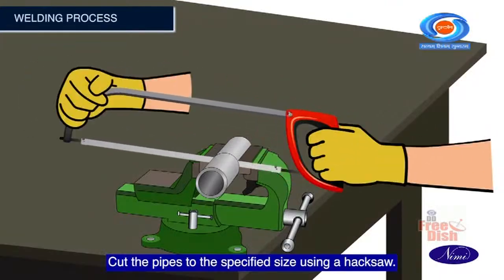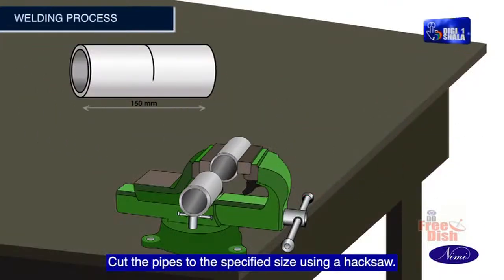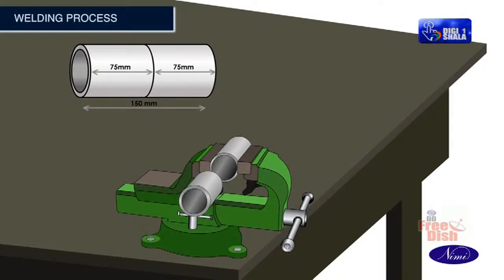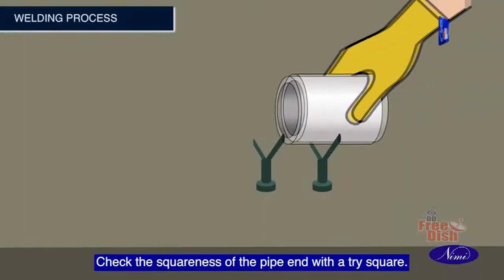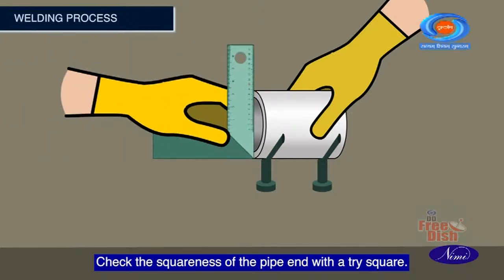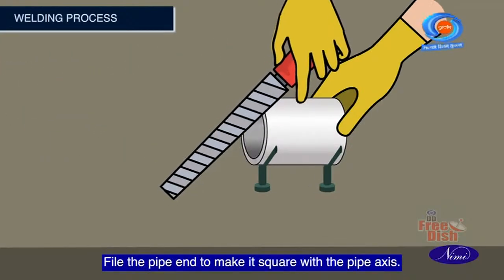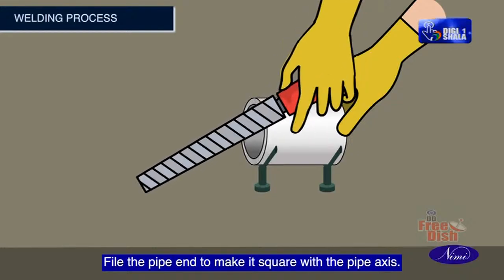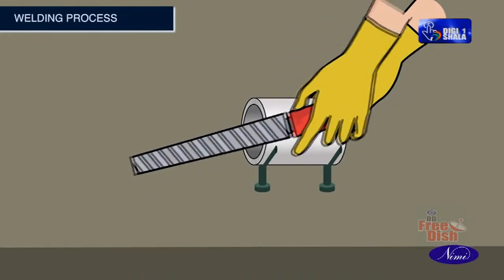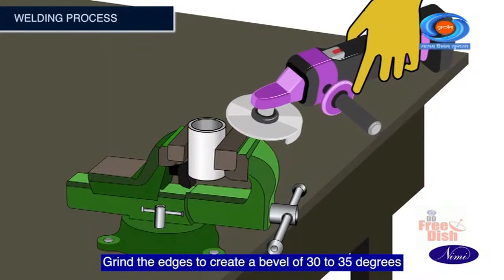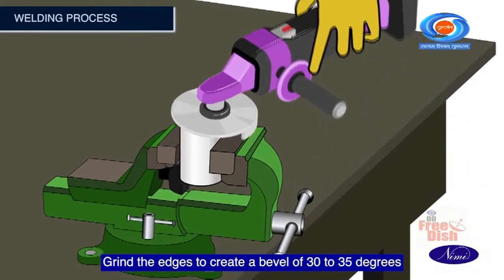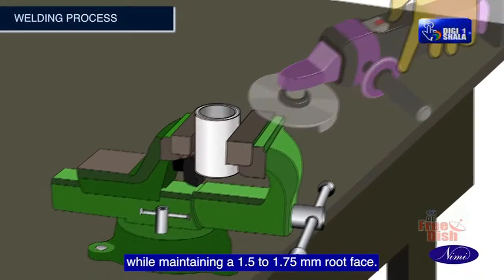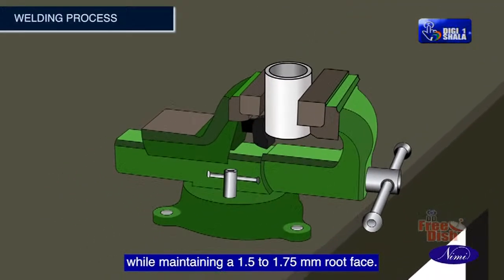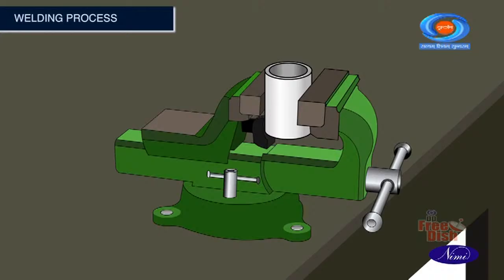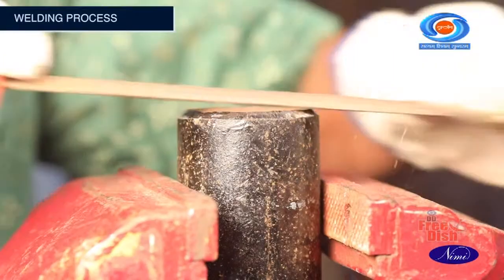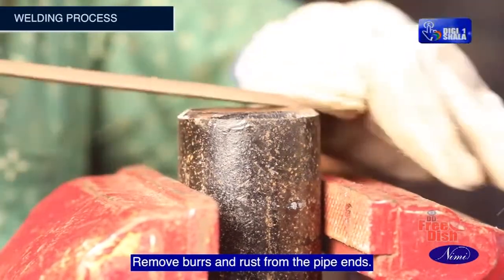Cut the pipes to the specified size using a hacksaw. Check the squareness of the pipe end with a tri-square. File the pipe end to make it square with the pipe axis. Grind the edges to create a bevel of 30 to 35 degrees while maintaining a 1.5 to 1.75 mm root face. Remove burrs and rust from the pipe ends.